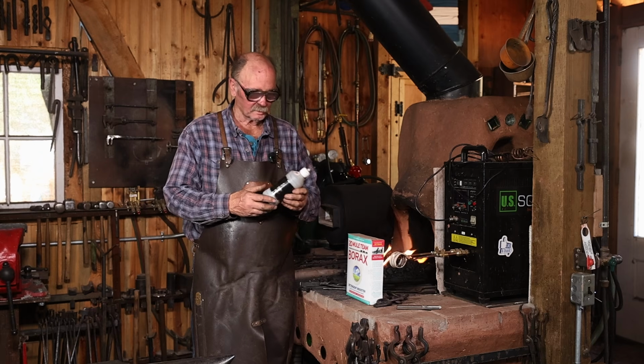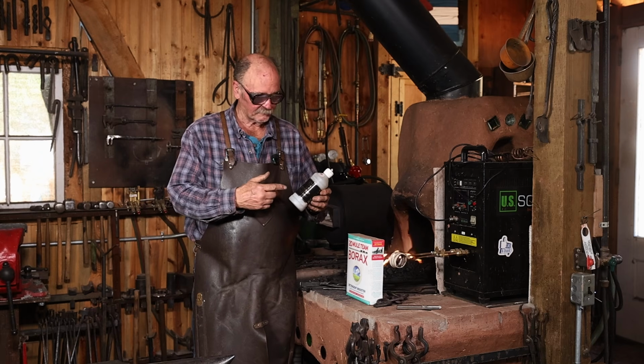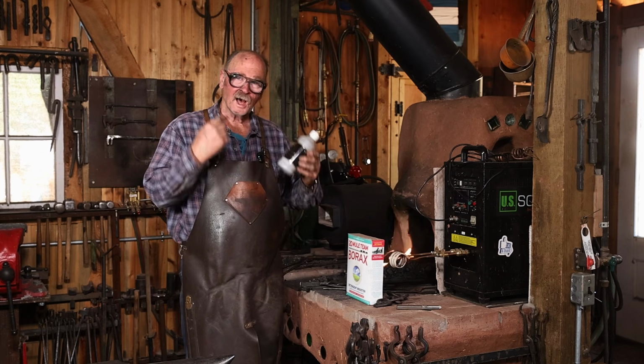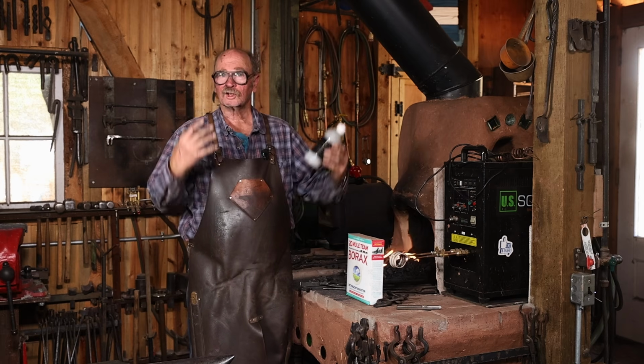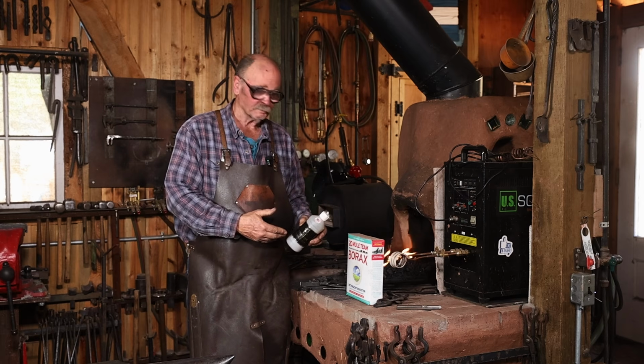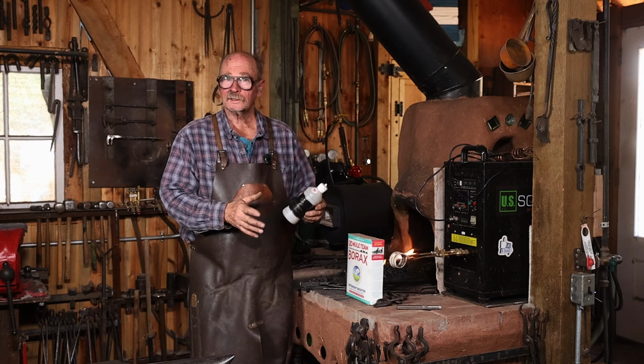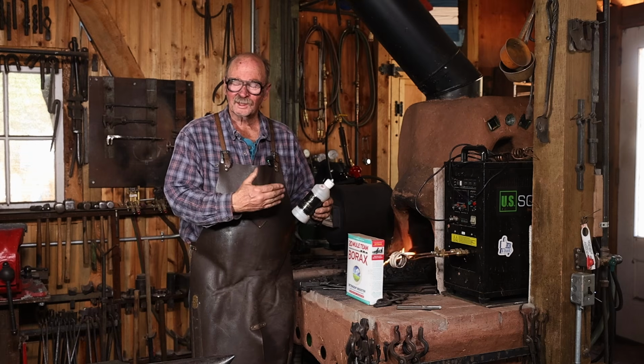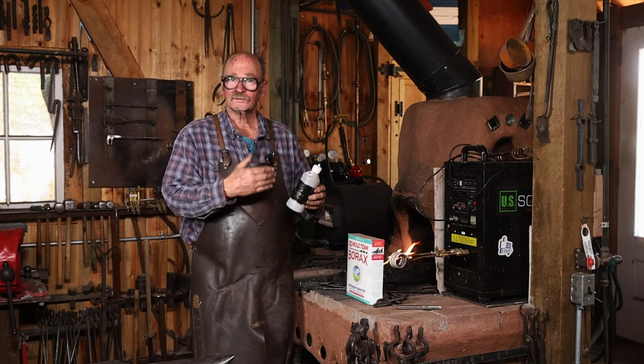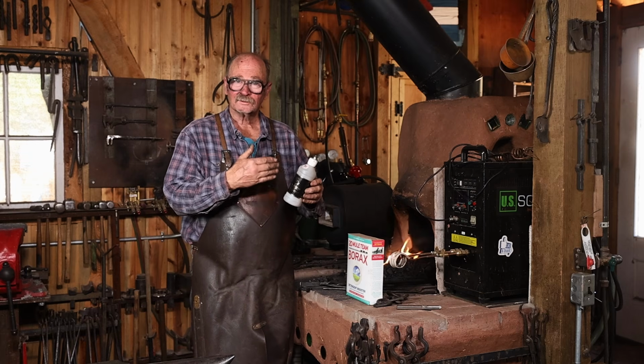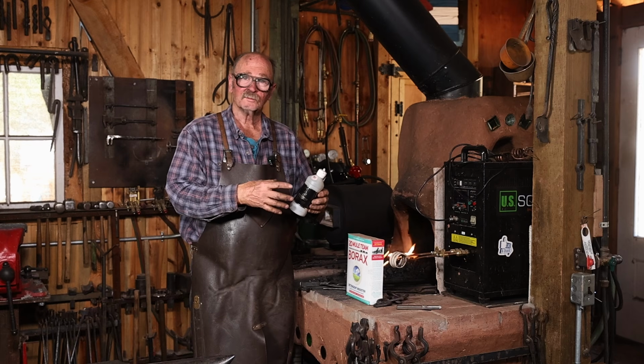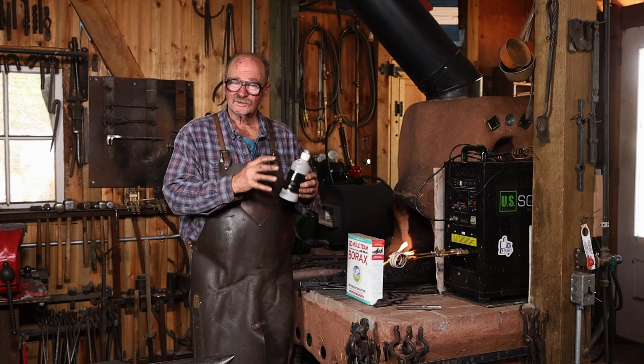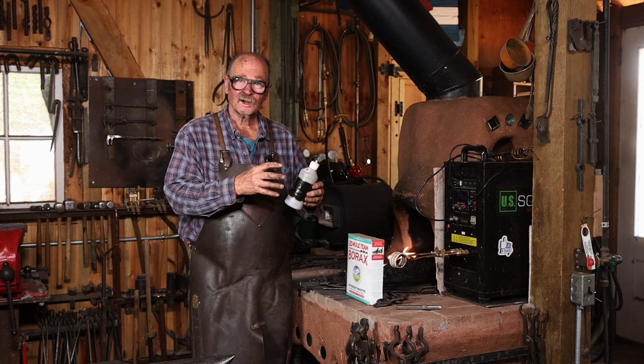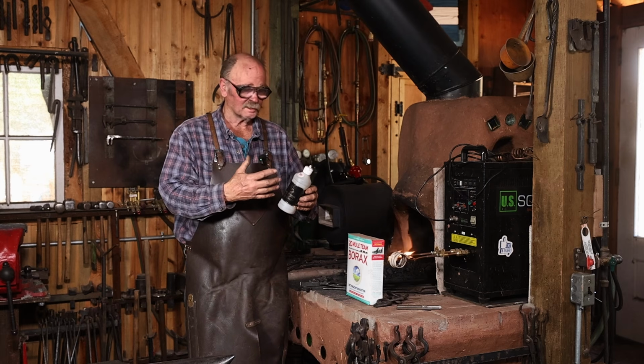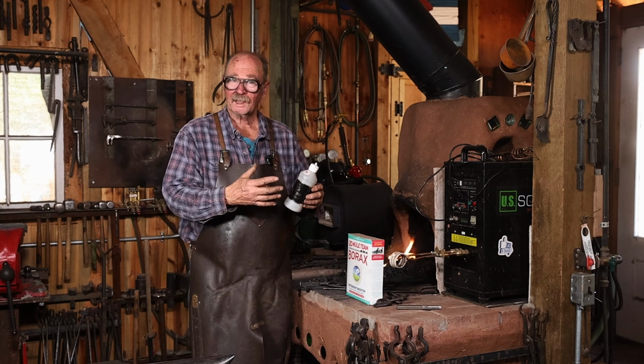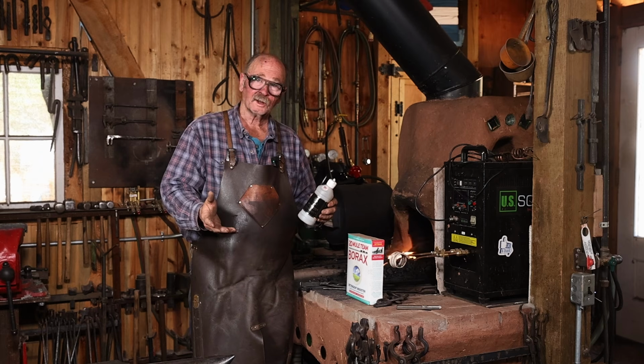Before we go any further in our discussion, let's talk a little bit about flux. Flux is not some sort of magic dust. It's not glue. It does not make the weld for you. You can weld without flux if all the conditions are right. Flux just helps a little bit. Its main goal is to clean the material. It dissolves the scale and crud that's on the material and kind of etches the material a little bit, leaving it cleaner. And then because it melts as it's doing this, it's sort of like a molten glass, seals oxygen out, helps prevent oxidation.